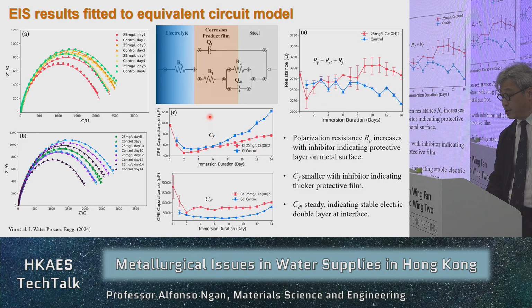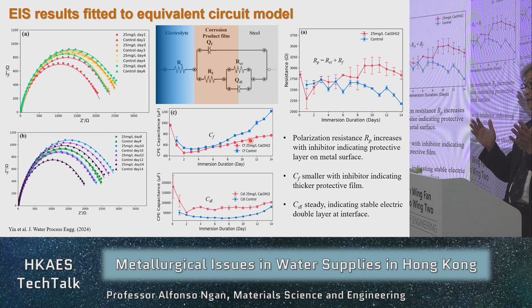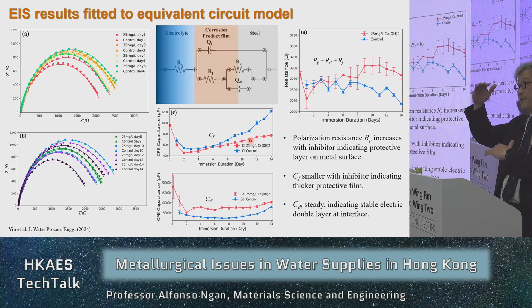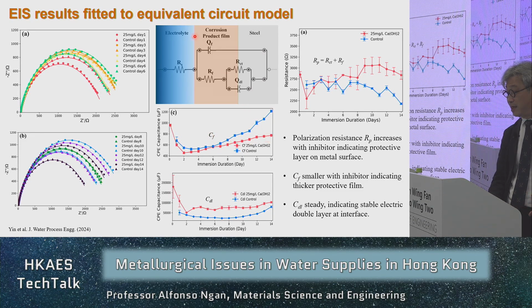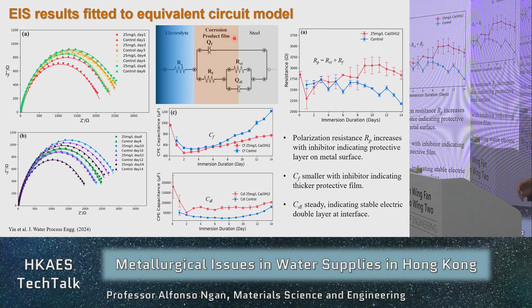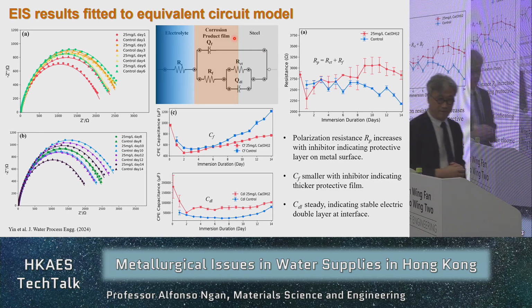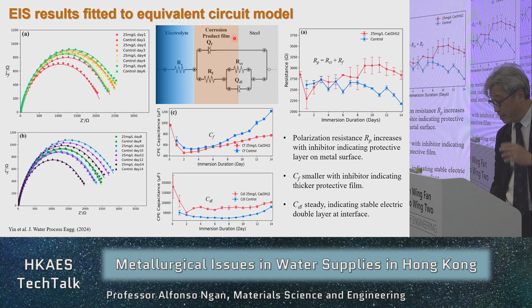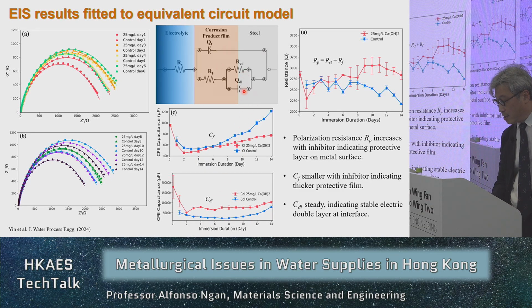You can also look at Cf, which is the capacitance of this capacitor, and for that, the Cf for the inhibitor group becomes smaller. So that indicates that, well, the capacitance is inversely proportional to the thickness of the gap of the capacitor, right? So when the Cf is smaller, that means that the gap here, or the spacing, or the width of this product film is larger with the inhibitor. So the inhibitor actually supports the growth of this so-called protective film or product film, which we will also understand what exactly that is later on. And the Cdl, the double layer, this one becomes rather steady. So that is not a varying factor.